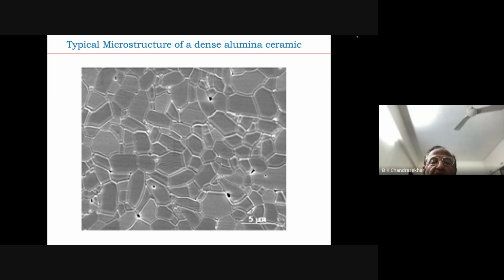Now, I talked about the microstructure of a typical ceramic material. If you look under a microscope, it will be like this. When you say average grain size, it is not all grains of the same size, they will all be different. The bar here, the white line, shows about 5 microns. Just by looking at it, some are maybe 5 microns and this one is very small, but what they do is calculate the average grain size. In this particular case, probably the average grain size is about 3.5 or 4 micrometers, which is good but not great.